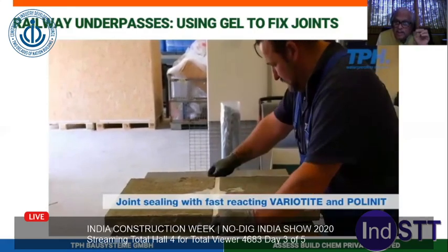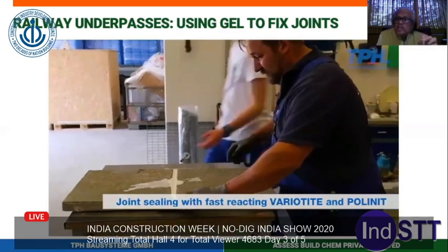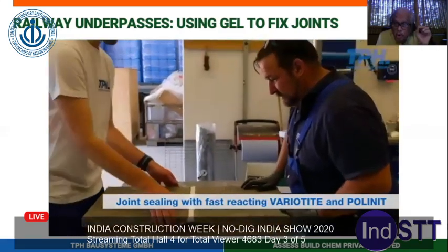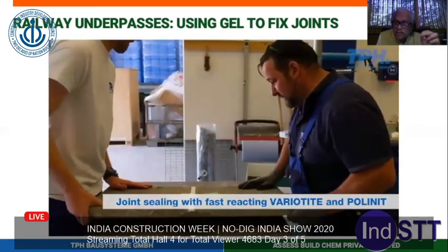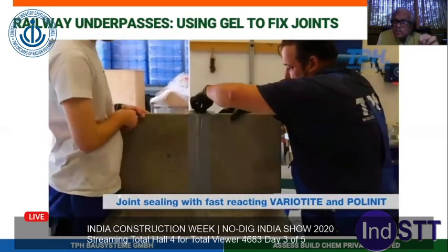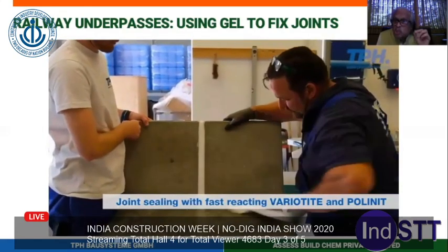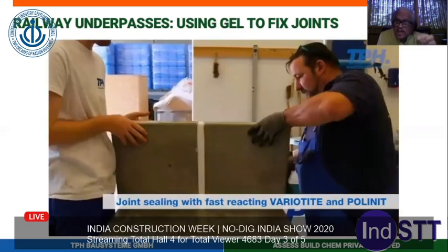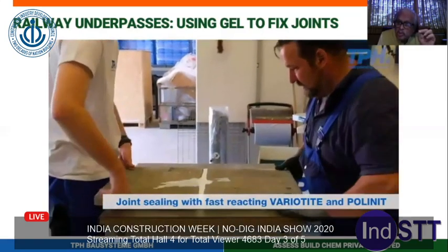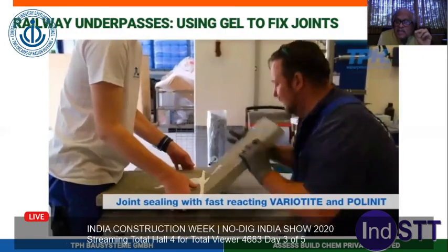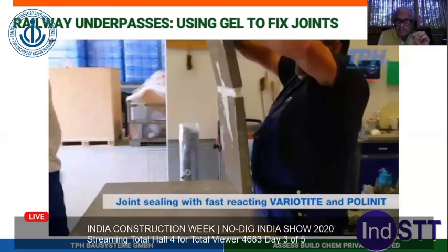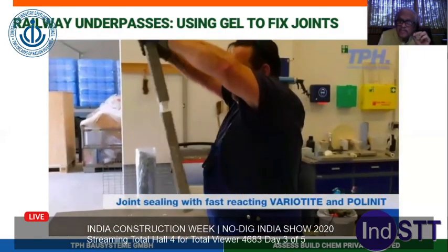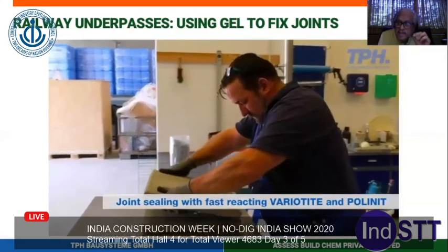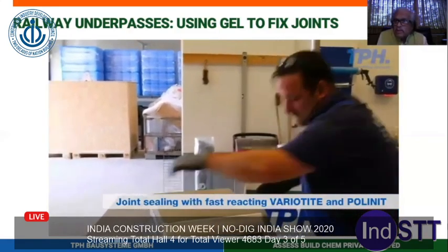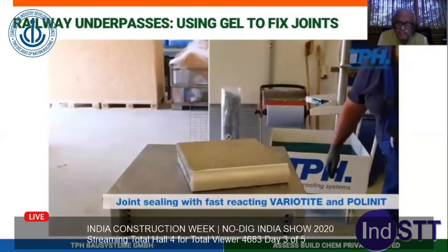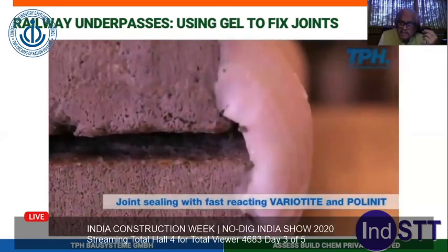Any material you are using to recreate the joints in the segments, or to recreate the joints for the underpasses, or any other joint from where the water comes, a joint is a joint. It is to be treated like a joint. The bonding should be there on the sides, and it should have enough elasticity. You can see here within 10 minutes, that means any water that is coming, it reacts with water, and it is totally elastic.